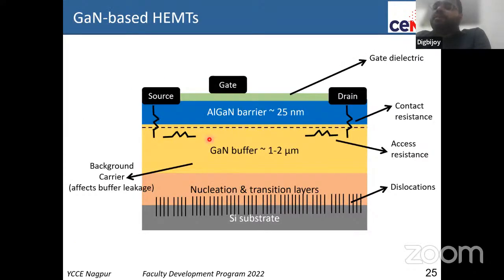Some people are trying to improve the contact resistance. Some groups are trying to reduce the impurity in the gallium nitride buffer so that more and more voltage can be blocked. Some groups in industry or academia are trying to reduce the dislocations here so that a fewer number of dislocations and defects can propagate. And some people try to remove the silicon substrate completely after growing, because the silicon breaks down when the field reaches the silicon, so you can improve the breakdown voltage. So there are n number of approaches to improve the device, to improve the material, engineer the stack, engineer the device, and so on and so forth.